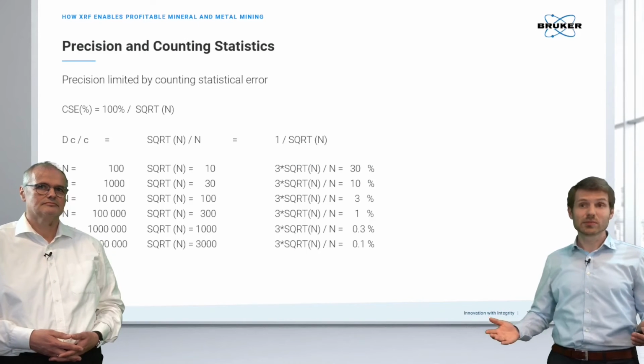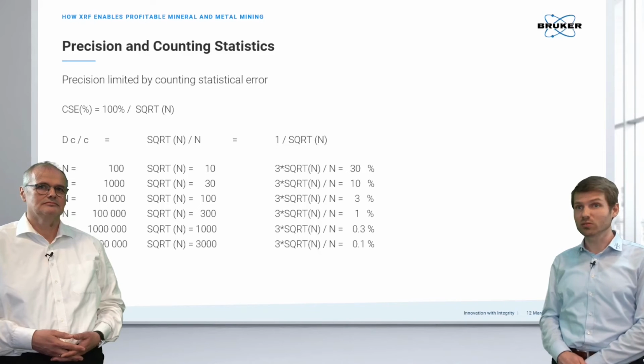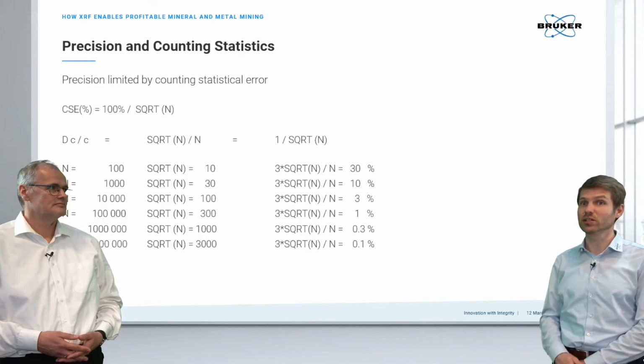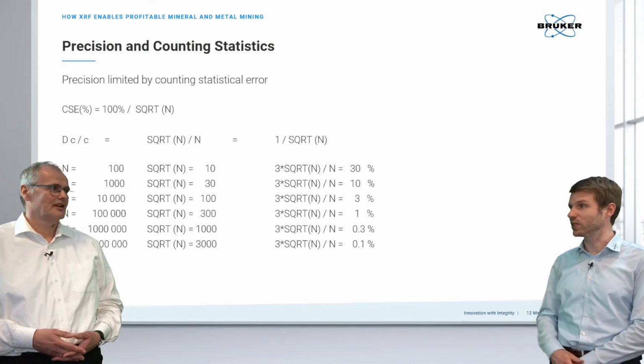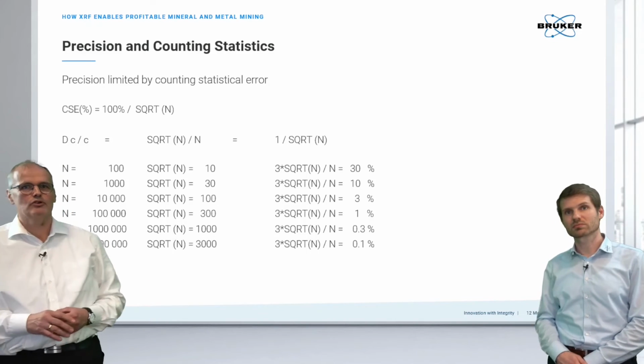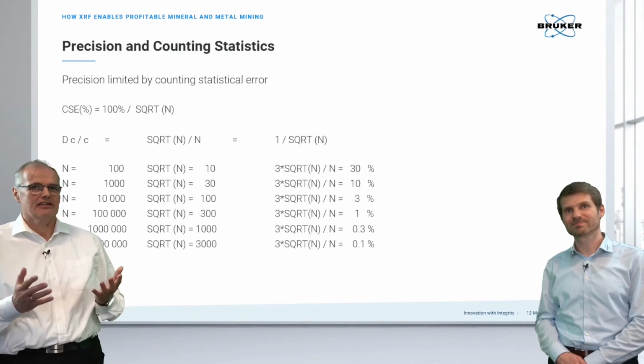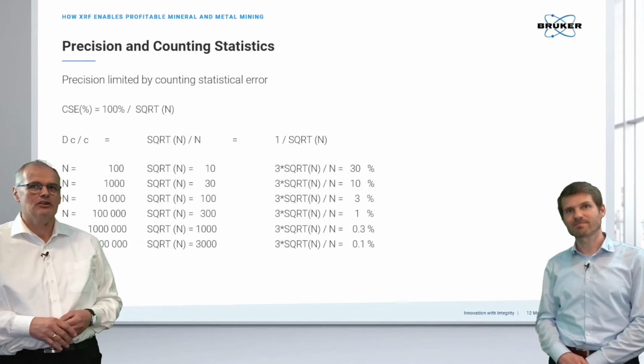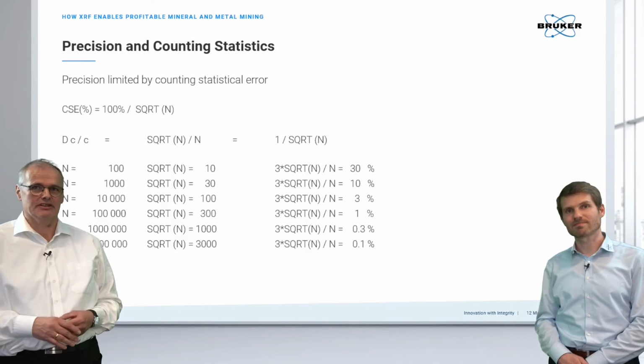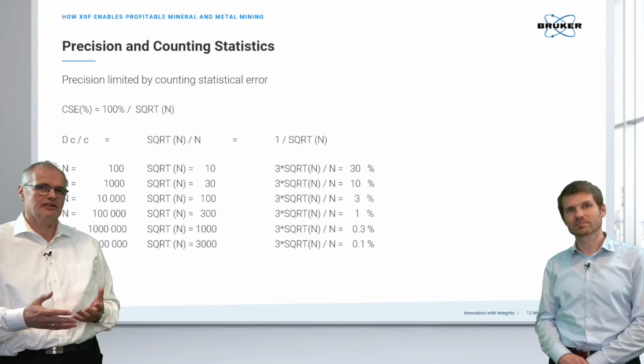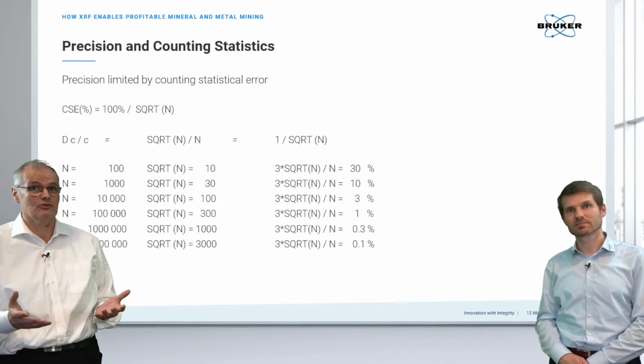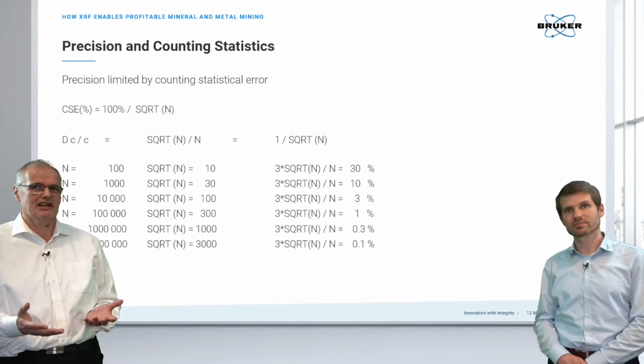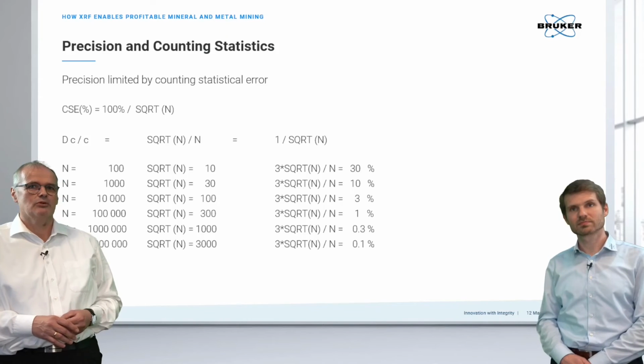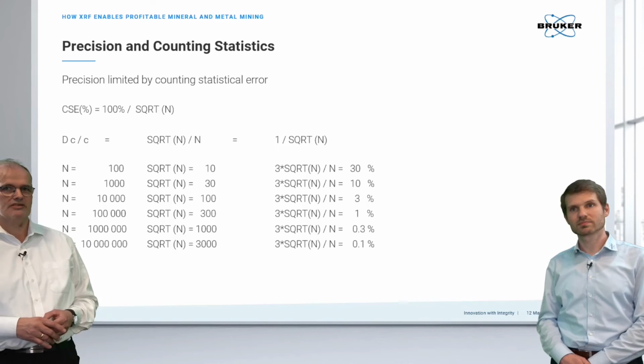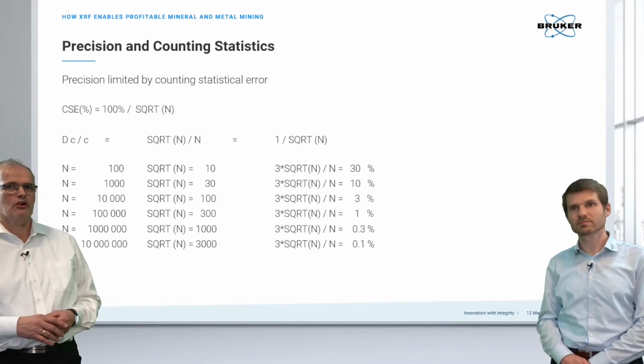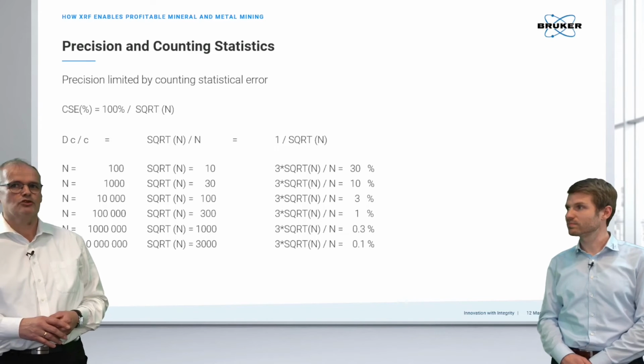But of course, there are some limits, and especially when it comes to throughput, counting and also lowest traces, counting statistics matter. And maybe Kai, you can elaborate a little bit about the matter of counting statistics. Yeah, I mean, I don't want to bore you with mathematics, but actually there is a principle. It means there's a counting statistical error, and this actually determines how precise we can be. And actually taken into account that we are having for one element 100 counts, total count rate, actually we will see that our counting statistical error is 30%. And in the moment we are adding more counts, we are bringing this down. So assuming that major elements we count with 10 million counts in total, we will go down to 0.1%.